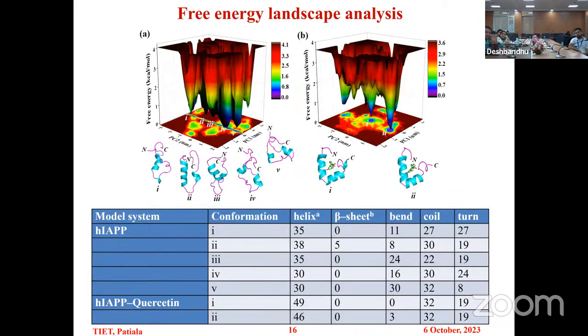Next comes the free energy landscape analysis, and from this analysis, we can clearly see that high energy conformation states were more in HIAPP in comparison to HIAPP in presence of quercetin. And this data shows the helix and beta sheet content, and we can clearly see that helix content was significantly increased and the beta sheet content was decreased, which shows the stability of our system.